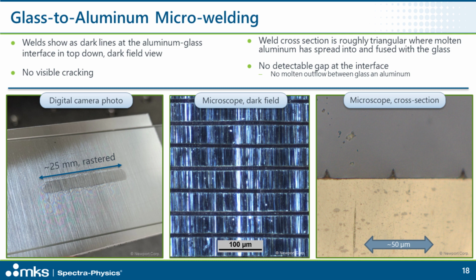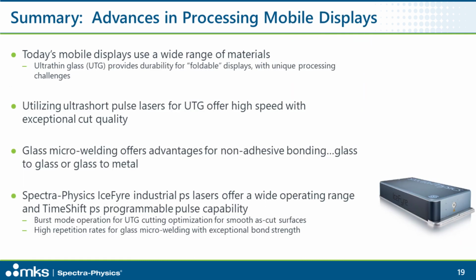We don't have strength test results, but we could break the glass off, and in breaking the glass off, the very large chunks of the glass remain bonded to the aluminum. So we're confident that there's quite a good welding achieved there. And that concludes the glass welding and cutting segment of the slides.